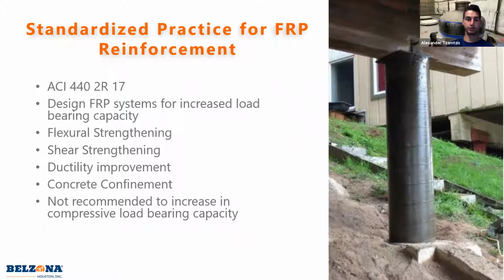So what we found was we had Belzona Super Wrap 2. If you guys aren't familiar, it's our ASME composite wrap. And to be compliant with ASME, you have to put that composite through a lot of different testing, anything from tensile strength to shear strength to elastic modulus, just a whole bunch of testing. So we took a look at the ACI standard and we realized that we already had all the testing that we needed to be compliant to this standard. So now we can use this standard and actually make some calculations and use that to do some jobs and reinforce concrete members, anything from flexural strengthening to shear strengthening to concrete confinement. We've been doing it for years. Now we have a way to calculate it with a standard.